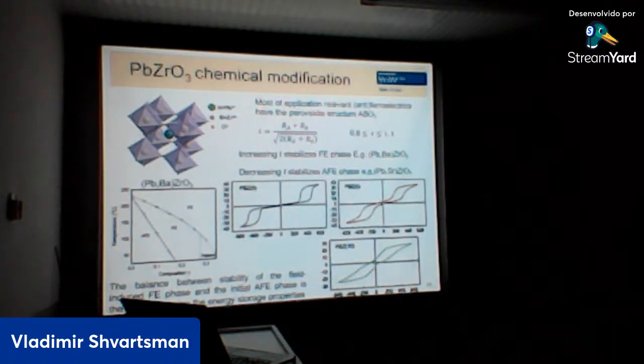You see that when we, for example, add barium to the lead zirconate, we increase the so-called tolerance factor. The tolerance factor is a geometrical factor to describe the packing of a cation in the perovskite structure. And this increase of the tolerance factor will stabilize the ferroelectric phase. On one side, we will decrease this critical field, which is good. From the other side, the ferroelectric state will finally become so stable that the remanent polarization will grow with the increasing amount of barium. So again, we have to keep a balance. The critical field should not be too low, but the ferroelectric state should also not be so thermodynamically stable. Then when we remove the field, it should disappear.